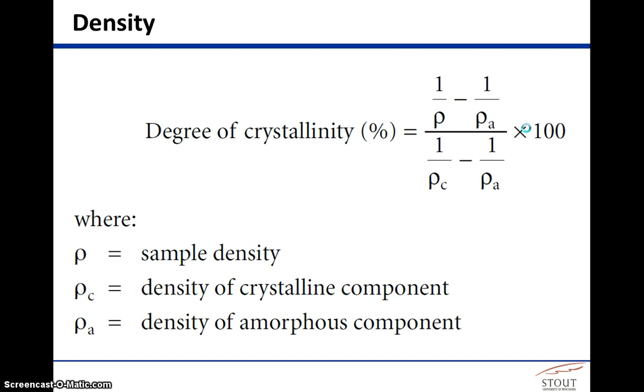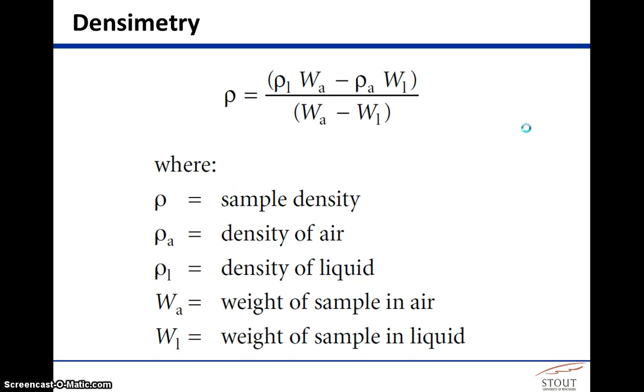If we first measure the sample density using a specific gravity measurement, you take your polymer sample, suspend it from a balance on a string, and place it in a beaker of liquid of known density. You measure the weight in air and then submerged in the liquid. Because we know the density of the liquid, we can back-calculate the density of the sample. The variables are: sample density, density of air, density of the liquid, weight in air, and weight in liquid — plug them into the equation and you get your sample density.